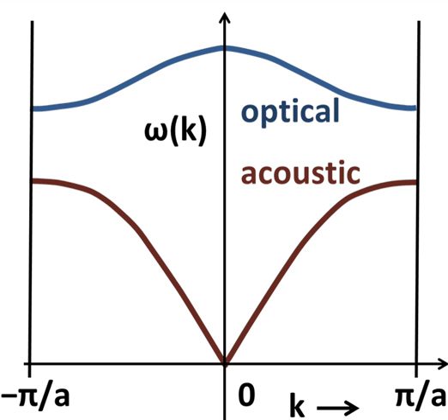By analogy to photons and matter waves, phonons have been treated with wavevector k as though it has a momentum ħk. However, this is not strictly correct, because ħk is not actually a physical momentum; it is called the crystal momentum or pseudomomentum. This is because k is only determined up to addition of constant vectors, the reciprocal lattice vectors and integer multiples thereof. For example, in the one-dimensional model, the normal coordinates Q and Π are defined so that Q_k = Q_{k+K}, Π_k = Π_{k+K},